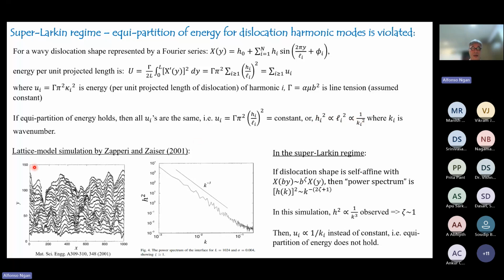So obviously, as these people have shown, this condition does not hold in the super-Larkin regime, where the dislocation shape is fractal. They have plotted h squared over k, and from their simulation, they found that instead of being proportional to 1 over k squared, h squared is just proportional to 1 over k cubed. So we have this conclusion: in the super-Larkin regime, where the dislocation shape is fractal, equipartition of energy of harmonic modes would not hold.